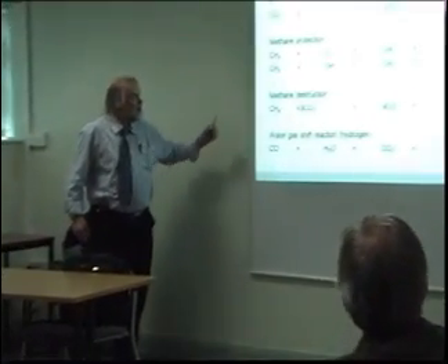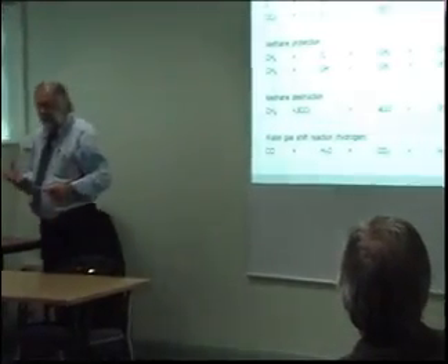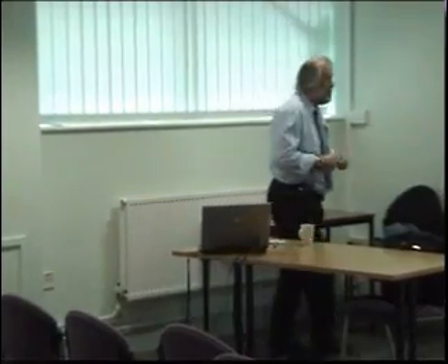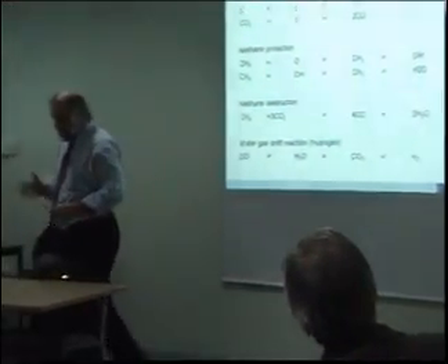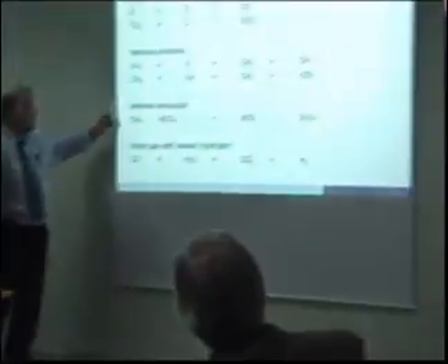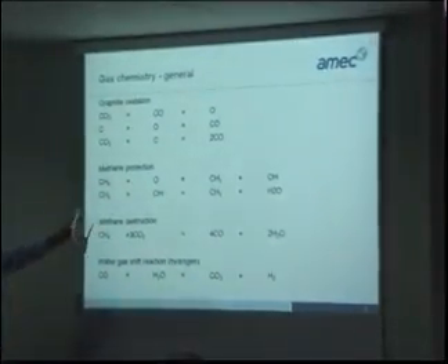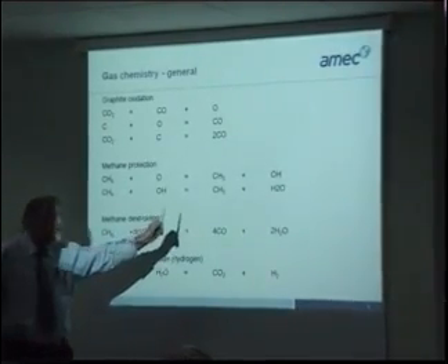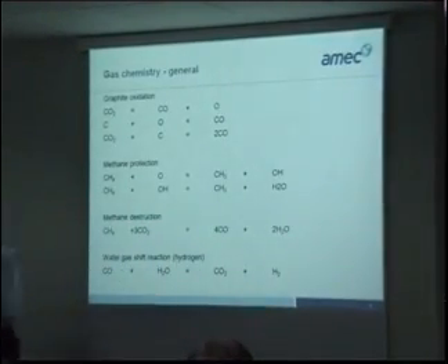Now, in order to mitigate the oxidation process from the oxygen atoms, we feed in methane, and methane is there as a reducing agent to mop up any oxidizing species. This mechanism produces methyl radicals and OH radicals, and there are follow-on reactions producing other hydrocarbons, both saturated and unsaturated. And with the reaction with OH, inevitably you're forming water vapour in the reactor.